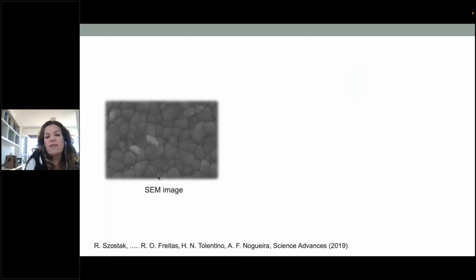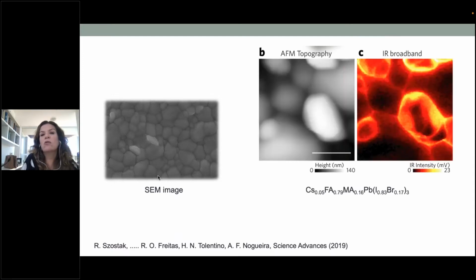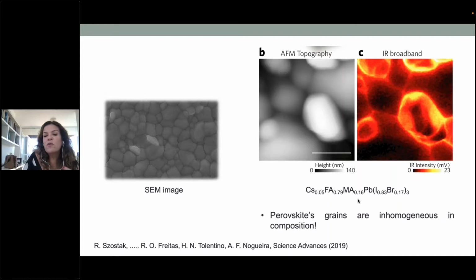So this is the normal image of the perovskite film. Here on the left you have the normal AFM topography. Here on the right you have what we call an infrared broadband image. What is interesting here is the same crystal. If you look at this crystal, you see that the intensity of the infrared light is different. What does it mean? What we know from this technique is that the organic cations of the perovskite absorb the infrared light. So because of the difference in intensity, you see that the perovskite grains are really inhomogeneous in composition.